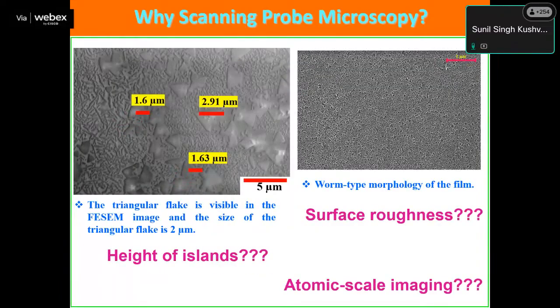These are two images of the surface morphology we have taken with the SEM, that is the scanning electron microscope. We can see the hexagonal or triangular 2D MoS2. Here we have the worm type morphology of the thin films. But from the SEM images, of course we can do cross sectional, but it is complicated. If you want to see the height of this 2D island, or this 2D layer on the silicon, we are not able to get it from the SEM.